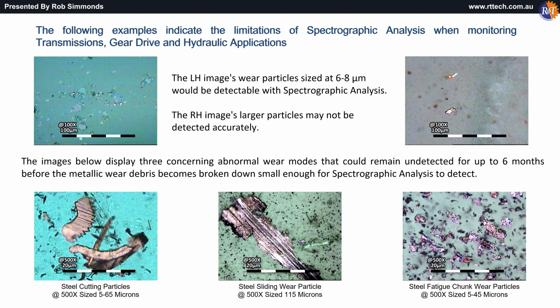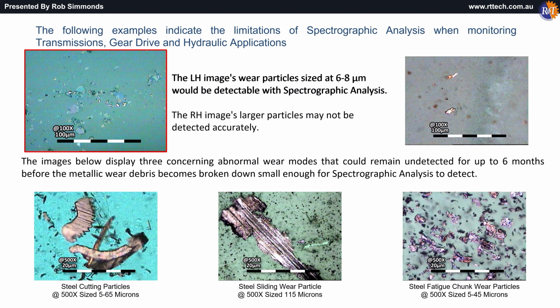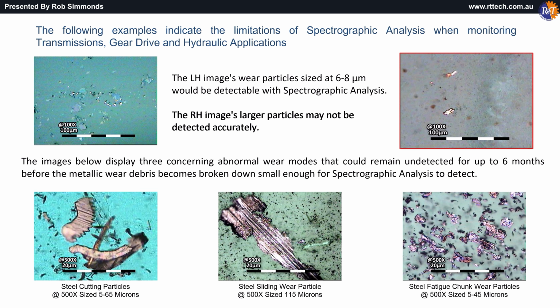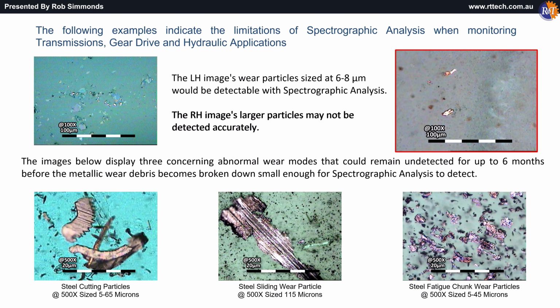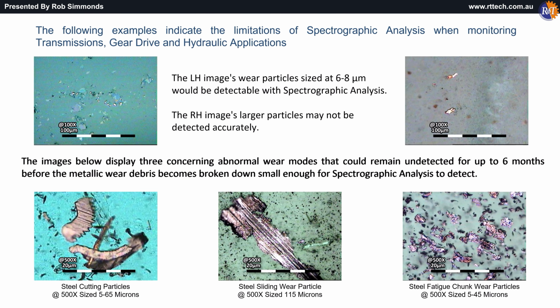The following examples indicate the limitations of spectrographic analysis when monitoring transmissions, gear drive and hydraulic applications. The left-hand image's wear particles are sized at 6 to 8 microns. These would be detectable with spectrographic analysis. The right-hand image's particles may not be detected accurately. The images below display three concerning abnormal wear modes that could remain undetected for up to 6 months before the metallic wear debris becomes broken down small enough for spectrographic analysis to detect.